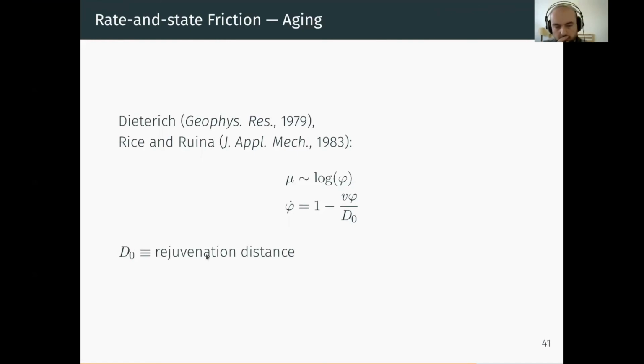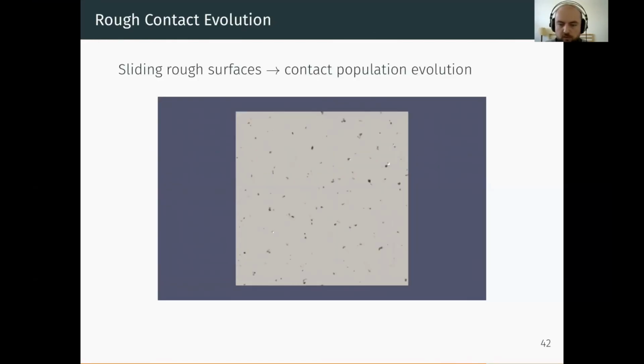So now when I started working on this, I asked myself what would be d0 in the case where we have those fatty acid coatings. And if we have roughness at the surface, typically d0 is interpreted as the distance you need to slide in order to renew your microcontact population. So if you have two rough surfaces that slide on top of each other, you have an evolution of the contact population, which you see here in this video. And d0 would be the sliding distance you need to lose memory of your previous contact interface, to renew your contact population.